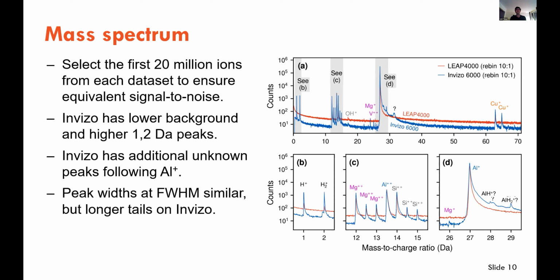Mass spectrum. So we choose the first 20 million ions from each data set to ensure the signal to noise is equivalent. There are also actually some interesting differences in the mass spectrum between the two instruments. So at least for the aluminium alloys, I found that there's a lower background in the Invizo by far, almost an order of magnitude, but significantly more hydrogen in that 1 and 2 Dalton peaks. Doesn't appear to be significantly more hydrogen elsewhere in the mass spectrum, but certainly in the 1 and 2 Dalton.